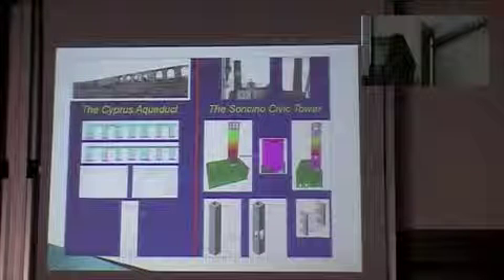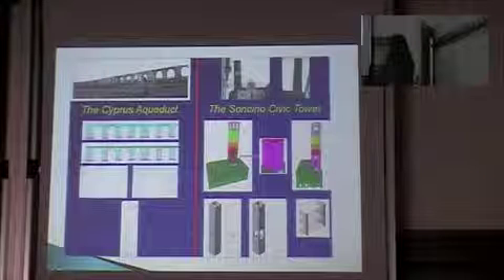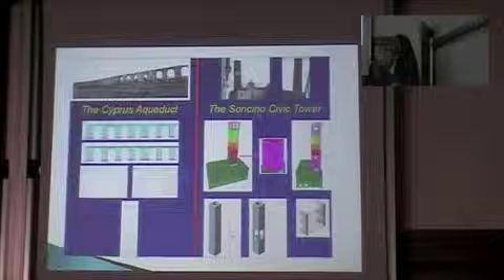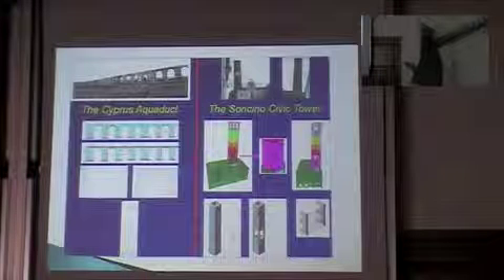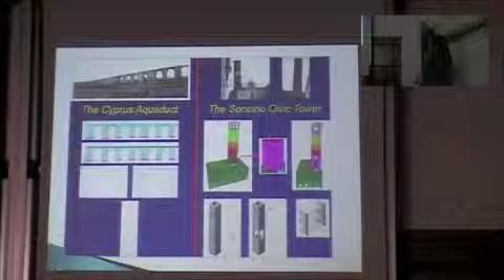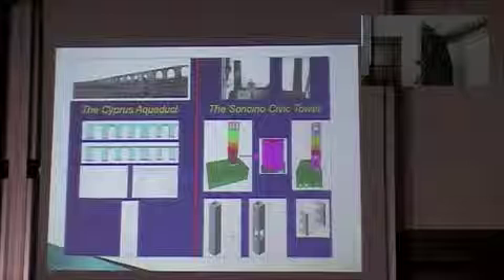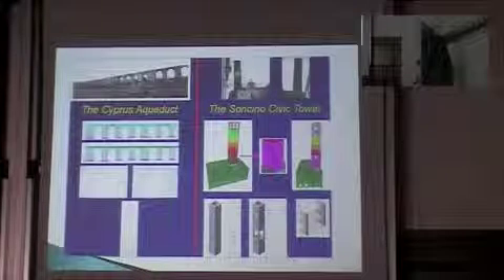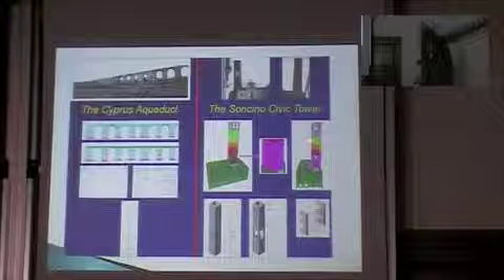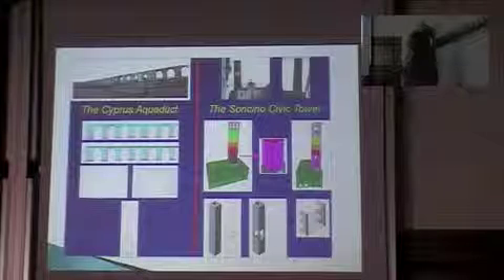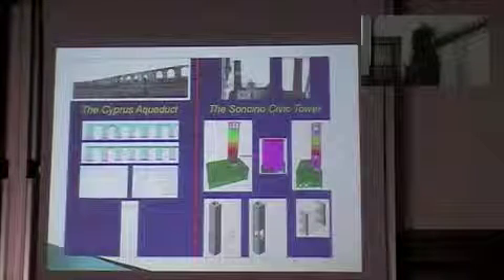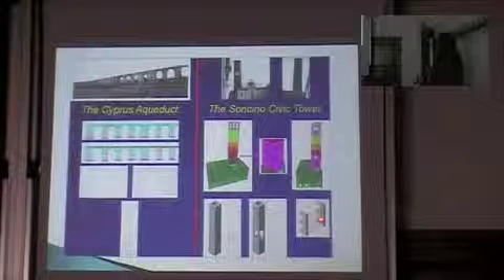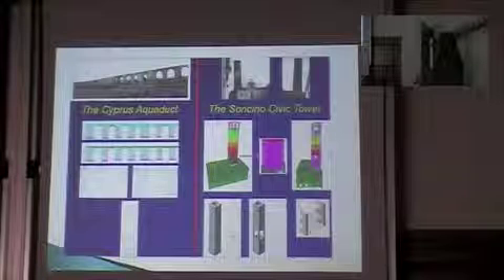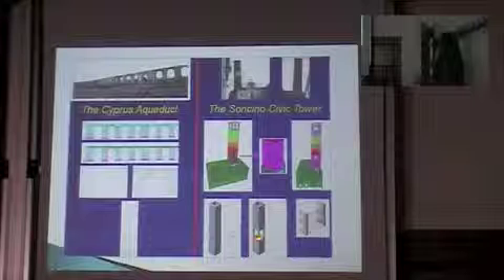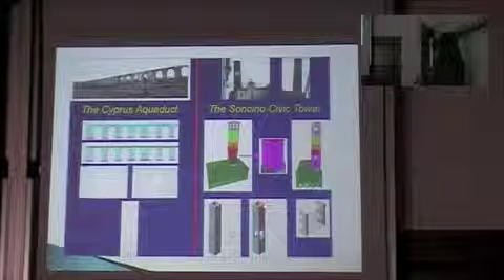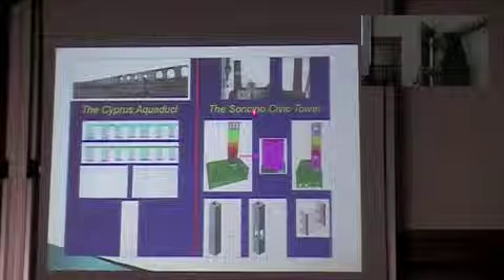And those are two other case studies. One, the Cyprus Aqueduct, they actually implemented the retrofitting, and it's still there and is being monitored. And there are students that are still analyzing the measurements of the retrofitted aqueduct. The Civic Tower of Soncino instead was the object of a monitoring campaign. It has not been retrofitted, it's still affected by pretty serious cracks. But here there was at least a proposal of retrofit where these devices were to be inserted where major damage was caused by the passing cracks. And we see how the experimental results once again could match the numerical ones.